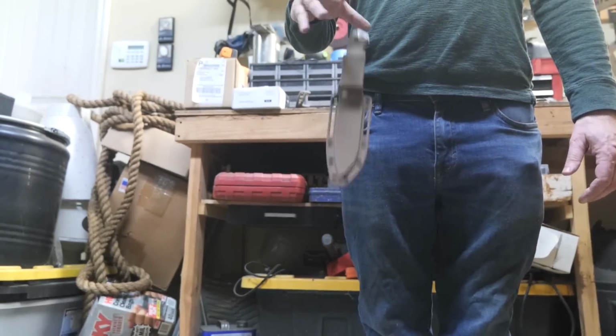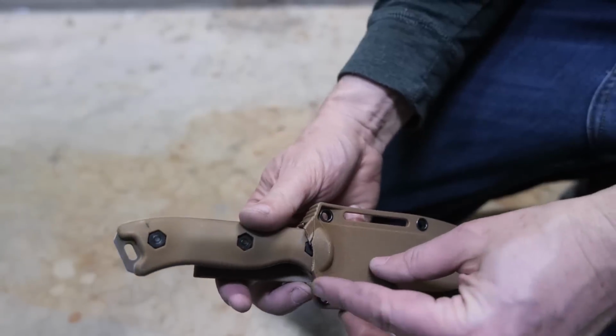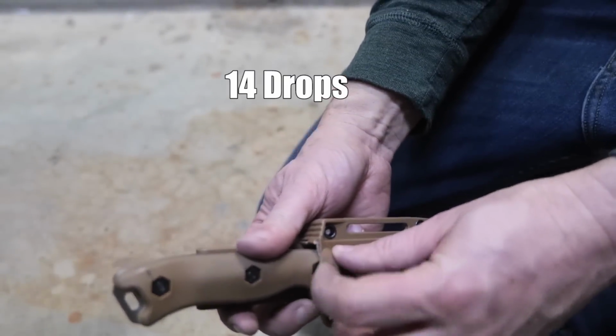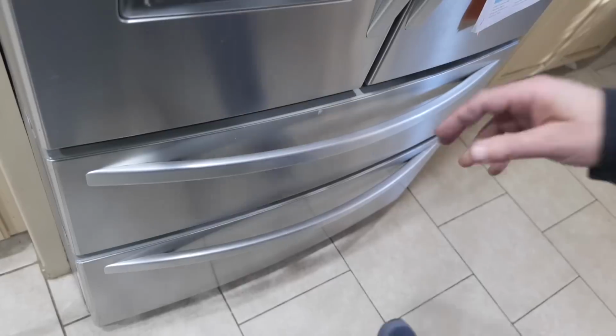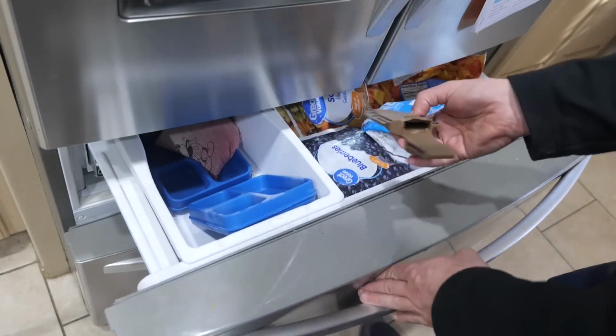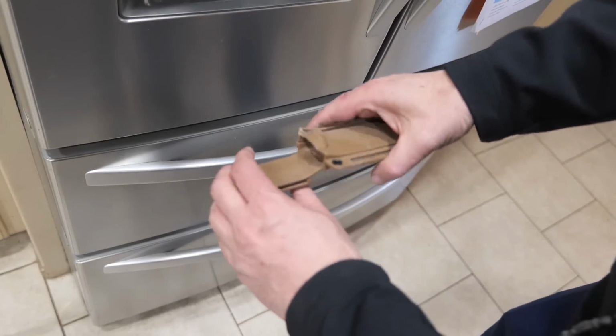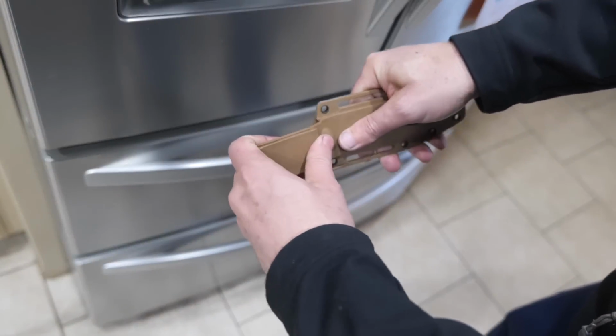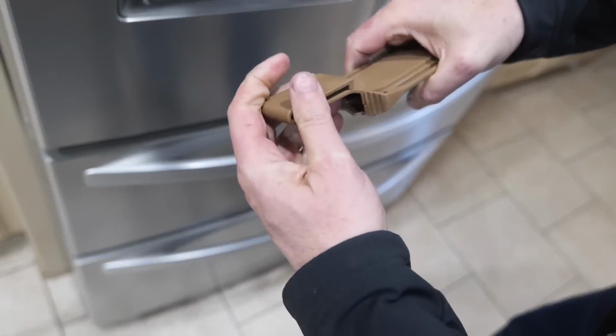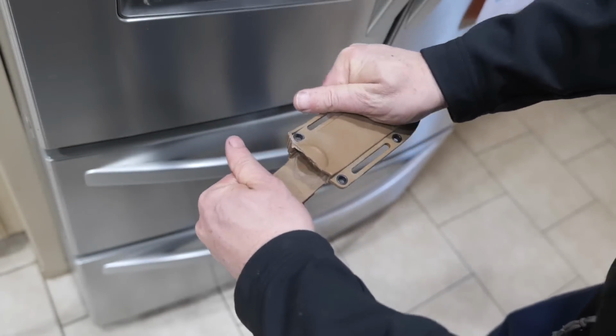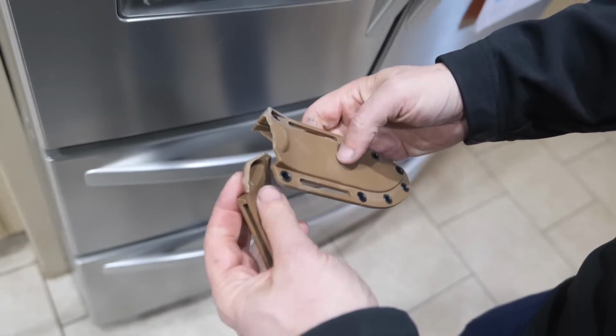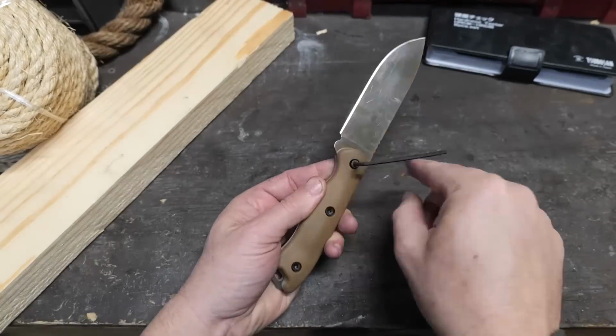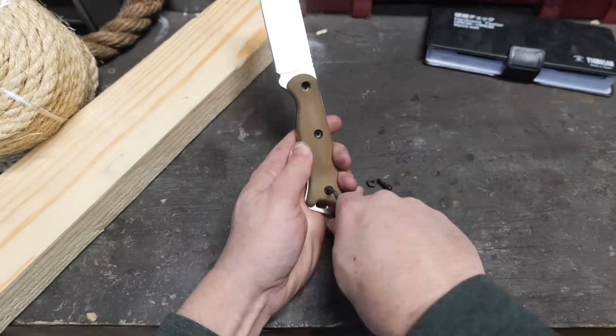Let's drop the sheath from hip height a few times and see what happens. So at 14 drops, it's broken. I've put it in the freezer to see how well it will tolerate cold weather. And with some force, the sheath breaks here. That's more than a little force, but not a lot. So the sheath is not as durable as most people would probably prefer, but at $12.82, let's be real. It's not mil-spec.